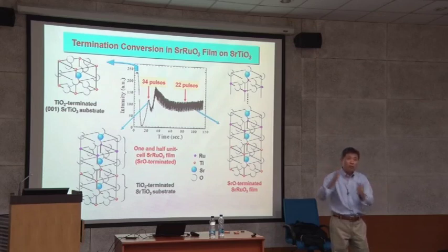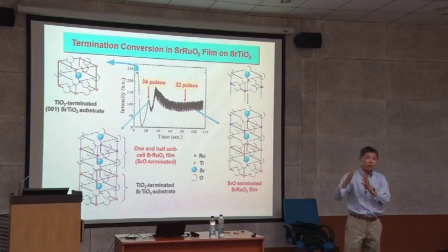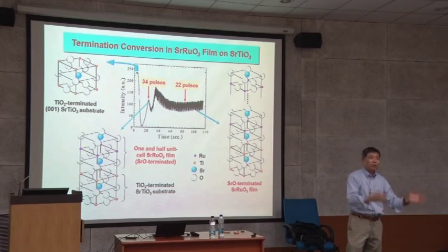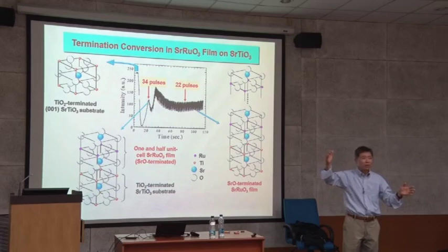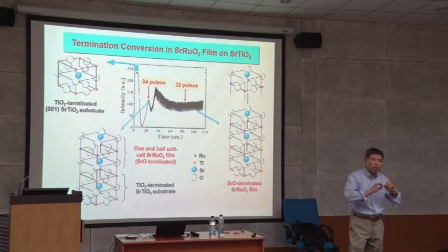Okay? You have to increase temperature. And if you go low oxygen partial pressure, you can do low temperature. So even the same material, you can grow from 550 all the way to 900. And then there's the approach I mentioned, just a pure metal source with ozone or atomic oxygen provided